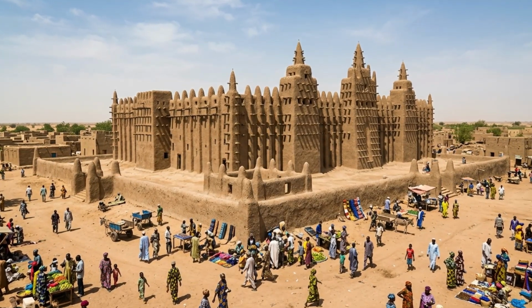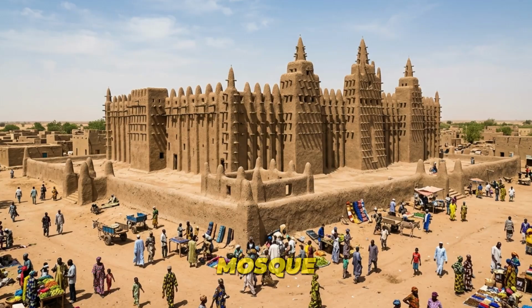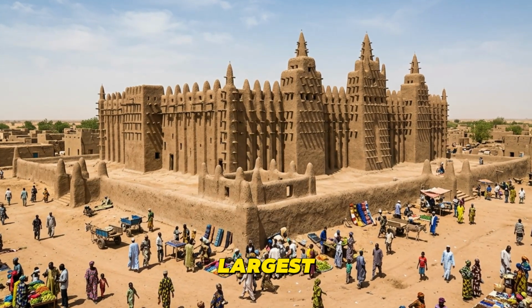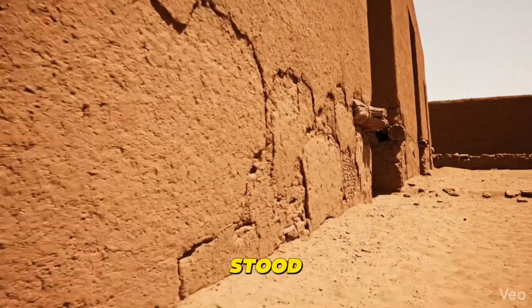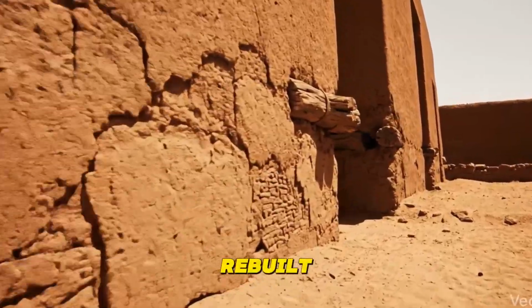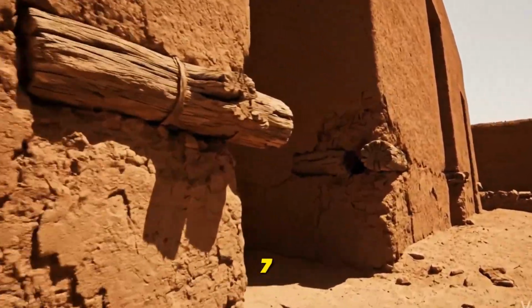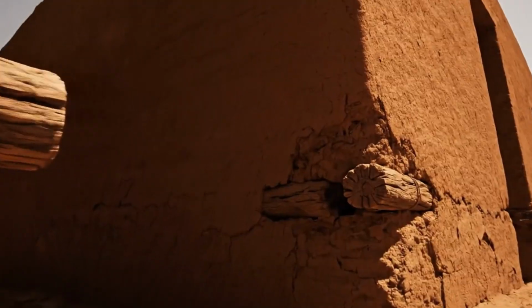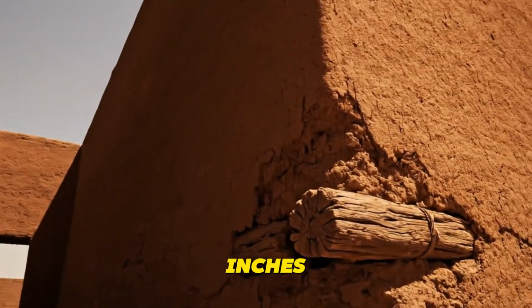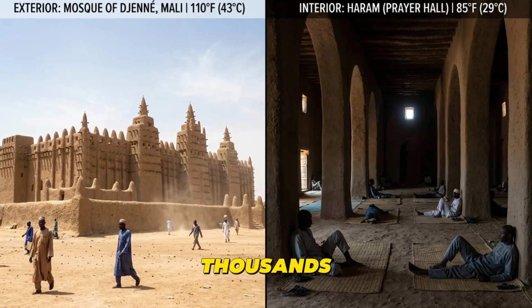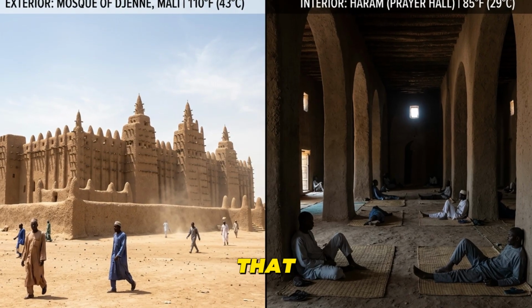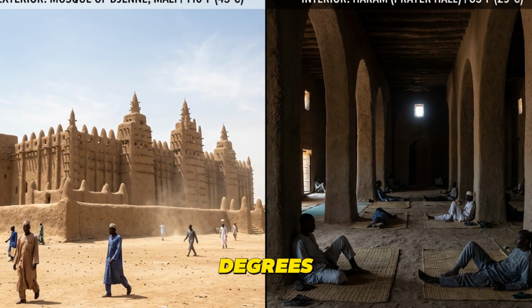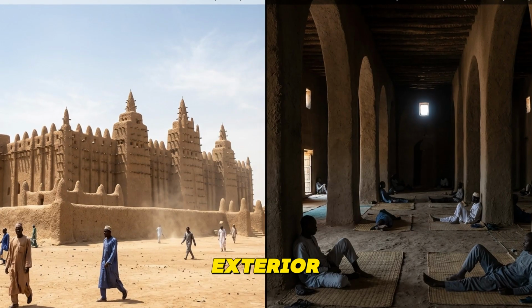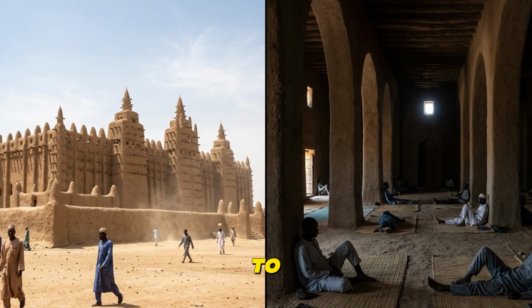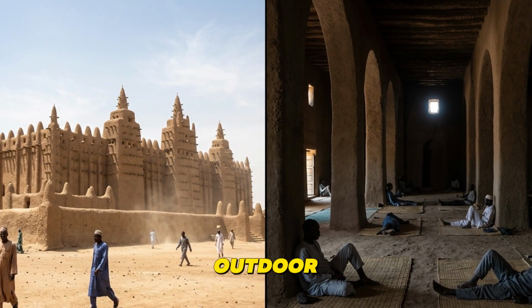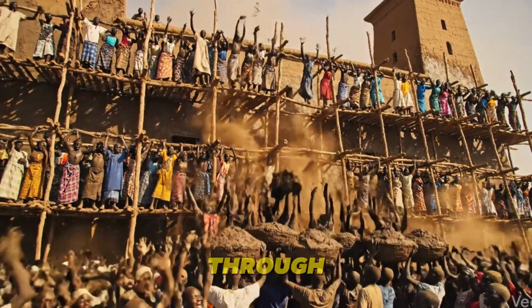systems. In West Africa, the Great Mosque of Djenné in Mali, the largest mudbrick building in the world, has stood since the 13th century, rebuilt to its current form in 1907 on the original foundation. The walls are up to 24 inches thick. The building shelters thousands of worshippers from temperatures that regularly exceed 100 degrees Fahrenheit on the exterior. The interior remains 15 to 20 degrees cooler than the outdoor air at peak heat, purely through the thermal mass